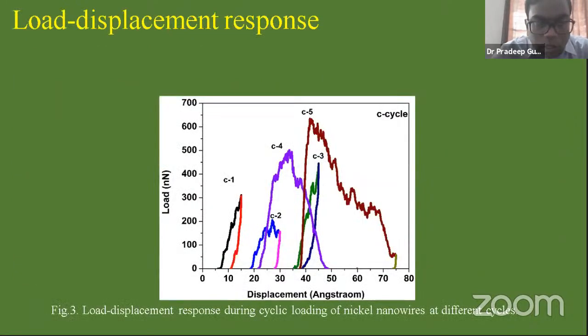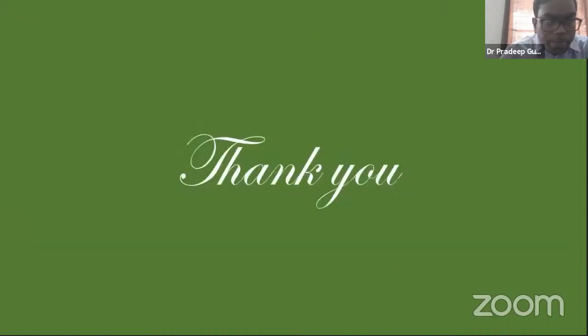Here are a few results I have included. This is the load displacement response of the cyclic loading of the nickel nanowire at different cycles. The cycles C1, C2, C3, C4, and C5 are represented here, and I have used multiple colors. For C1, the black color is for loading and the red color is for unloading, and vice versa. We can see the load increases continuously from C1 to C5, and we expect to get a similar kind of result in our simulations. So these are the references we are using. Thank you.